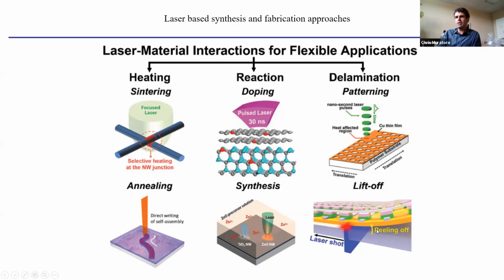Now, on the contrary, we used a low shear layer, that boron nitride layer, to detach the GaN device from the substrate in the previous example. What we're going to do here, you're going to use a laser, and we're going to have a sacrificial layer between our device and the substrate. That sacrificial layer is going to be a great absorber of the wavelength of laser that we're using, so that it basically ablates as we pass the laser over the surface, through the underside of this device. The device is up here, here's the substrate, and here's the sacrificial layer that I'm annihilating with the laser because it absorbs the laser energy preferentially. This substrate allows the laser to pass through, and I'm ablating this sacrificial layer, enabling transfer of the device here.